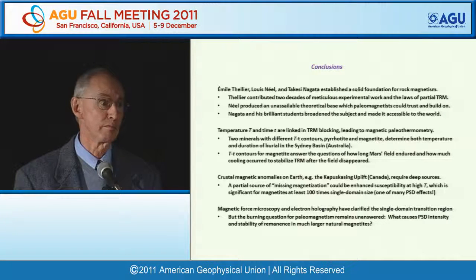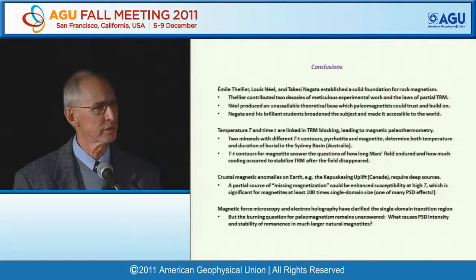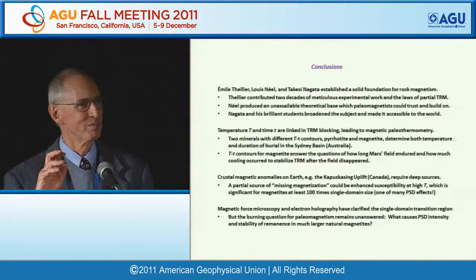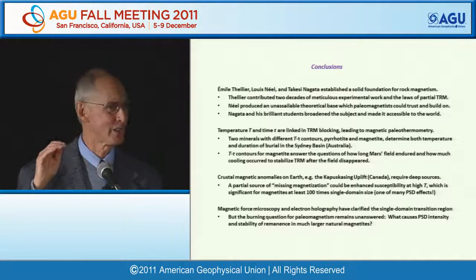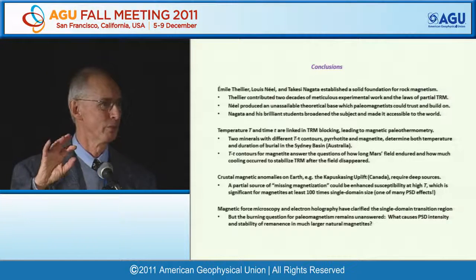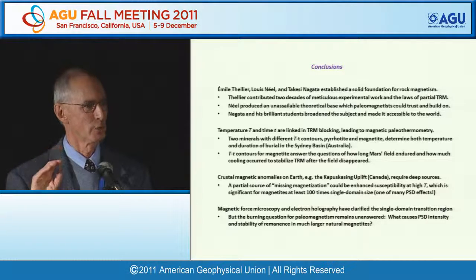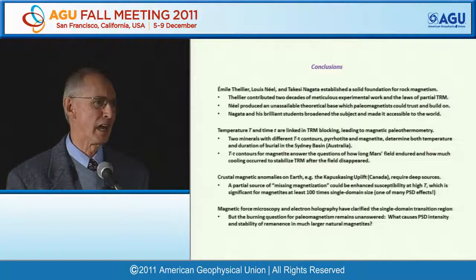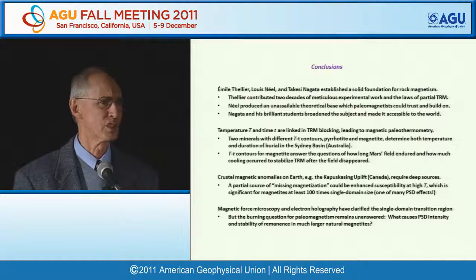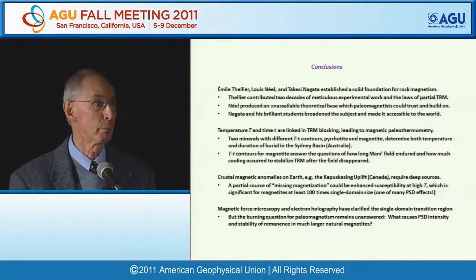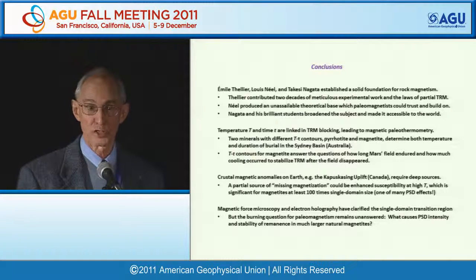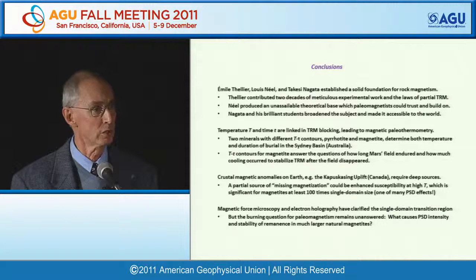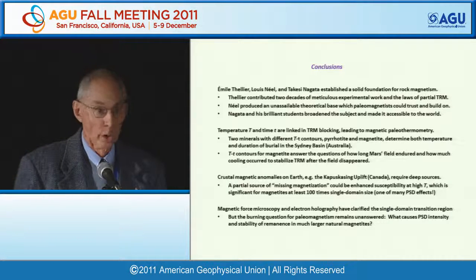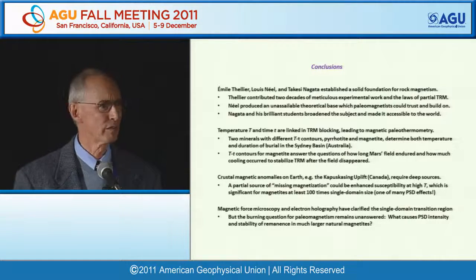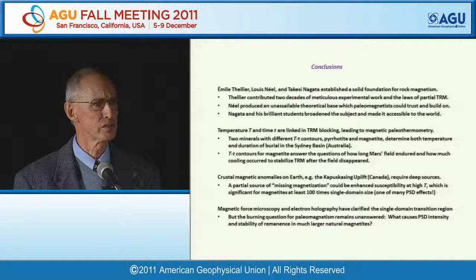Many people have made suggestions, but it's really very difficult to explain this. This is why we call into play the entire crust. It's just to try to get 30 or 40 kilometers of source material. Even then, we have to go to intensities of magnetization of something like 10 amperes per meter, which is like a fresh mid-ocean ridge basalt. But unlike MORB, this has to stay unchanged for a long period of time. No, I have no special insight.